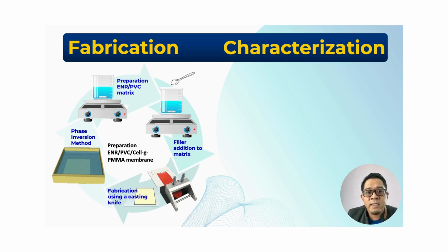Turning a liquid phase into a solid state is known as phase inversion, to remove the THF solvent and enable the creation of the ENR PVC cellulose grafted PMMA film. The solution is rapidly evaporated and then immersed in distilled water before being removed from the glass plate and allowed to dry at room temperature until sufficiently mature for additional analysis.